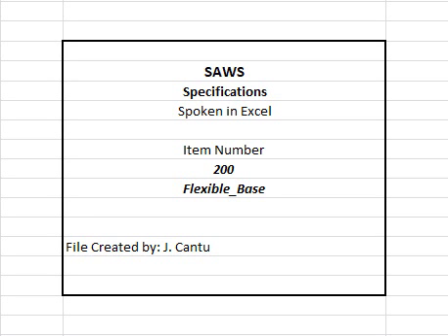200.6 Construction methods. The flexible base material shall be placed on the approved subgrade, in courses not to exceed 6 inches compacted depth. 1. It shall be the responsibility of the contractor that the required amount of material be delivered and uniformly spread and shaped. 2. All material shall be removed from the place where it is dumped by cutting into windrows. 3.